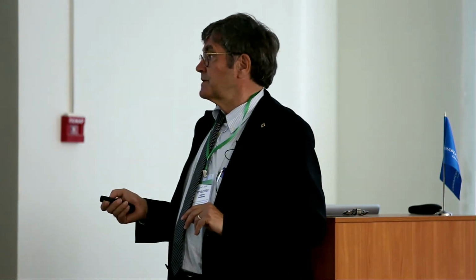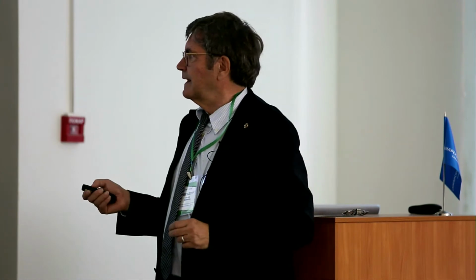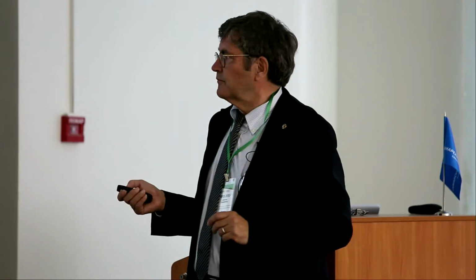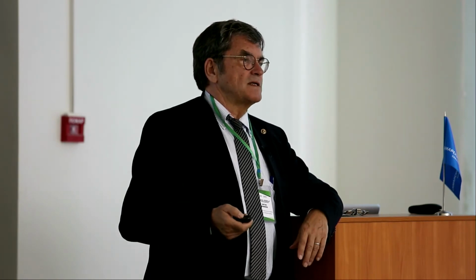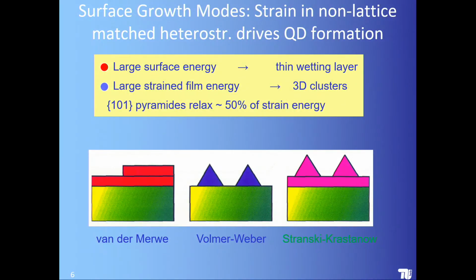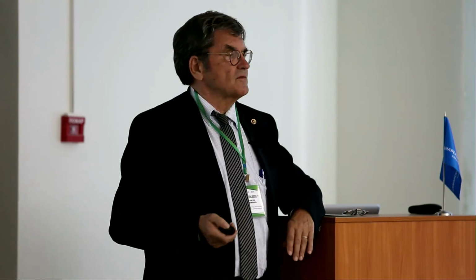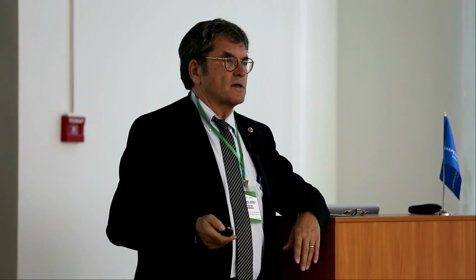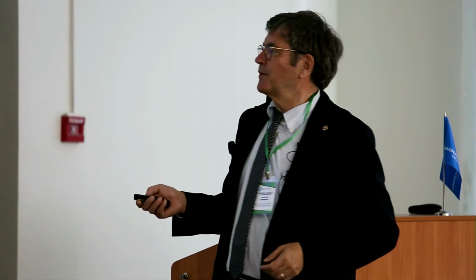Then, end of the 30s, a Bulgarian scientist, Ivan Stranski, found out there is a hybrid of both. You start with a thin wetting layer, and after that you have a first order phase transformation on the surface, and you get clusters which can be coherent clusters. The first results of this work were presented in 1938 at a meeting of the Physical Society of Vienna, which was the first before the Austrian Academy of Sciences came into existence. Yeah, 38. Stranski later on moved to Germany, always Bulgarian, and became professor at Technical University of Berlin after Second World War, and was the successor of Volmer, and became president of Technical University in 1952, still having a Bulgarian passport. I think this is a very nice historical side note of science history.